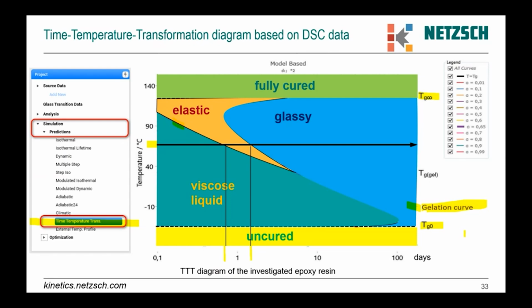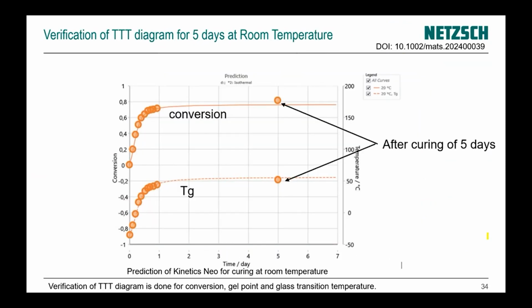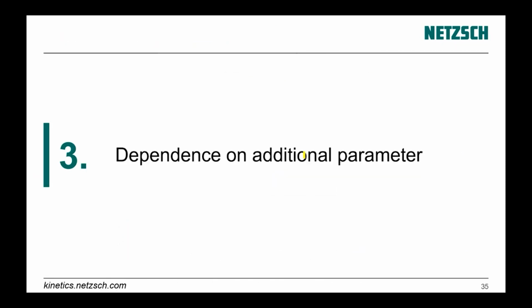And now, of course, we must validate this process. We did the following really long measurement. We put our two-component system at room temperature for 5 days. After these 5 days, we made a measurement in order to find the glass transition for this partially cured material and the degree of conversion for this partially cured material. And we found that the glass transition and conversion for this long validation time are in agreement with our predictions according to the time temperature transformation diagram. So this diagram works and we can use it in order to find how the curing goes on and where the glass transition and gelation point are.